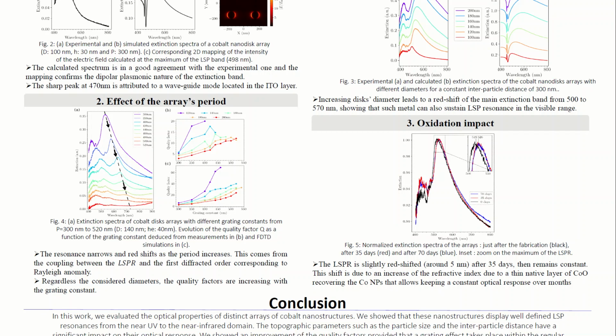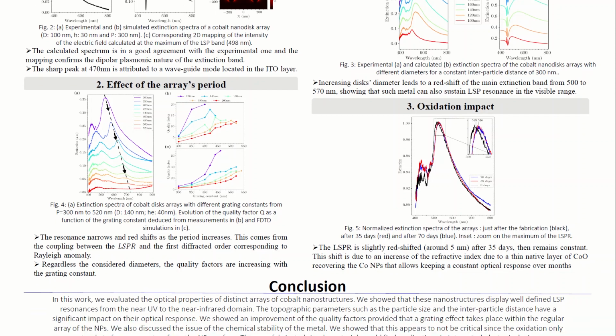A relevant question now is the chemical stability of the metal in air. We show that the resonance redshifts a little after 35 days, then remains constant. This shift results from the increase of the refractive index of the surrounding media due to the thin layer of cobalt oxide covering the nanoparticles, which allows the resonance to remain constant later on.